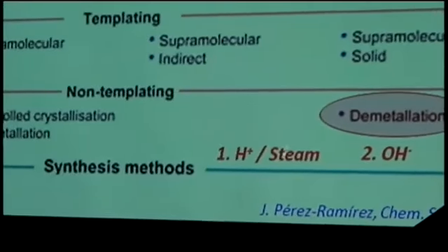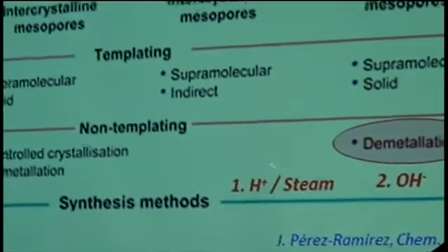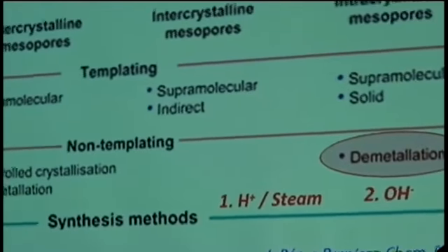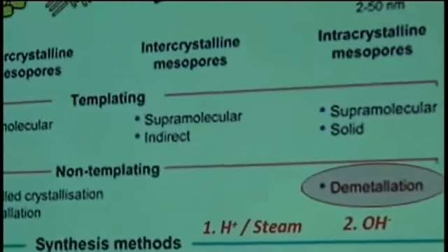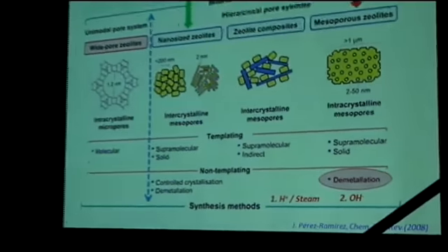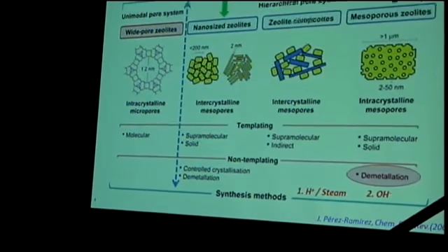leaching with acid. Basically, if you steam or if you leach with acid, you expel mostly aluminum from the framework. If you make a treatment with a caustic solution, for instance, sodium hydroxide, what you are doing is much more complex, but basically you selectively remove silicon now from the framework.